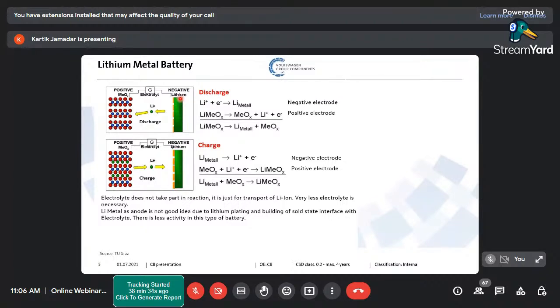There is a lot of lithium available. So this battery can give you very high ampere hour because there are a lot of ions available inside it. Plus the voltage is decided by the two metals, which is fixed. So voltage cannot be changed. Voltage is decided by the material, and the capacity is decided by the mass of the lithium ion. And since I've got a good abundance of lithium ion, this battery would theoretically be giving me maximum around, I would say, 10 to 11 kilowatt hour per kilogram. That is extremely high energy. Unfortunately, this battery does not exist.